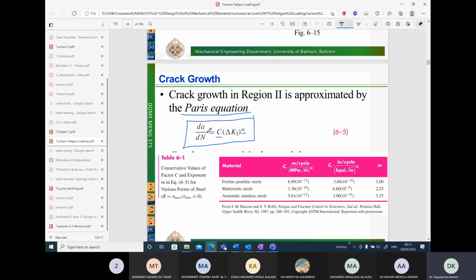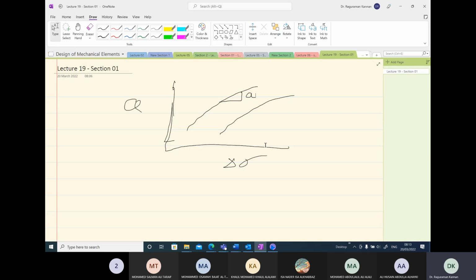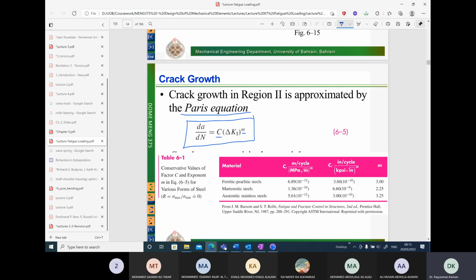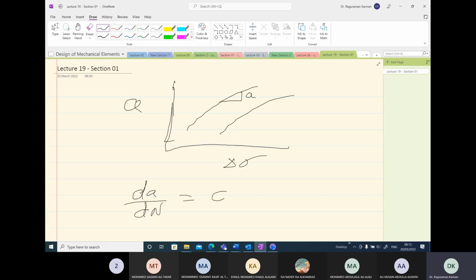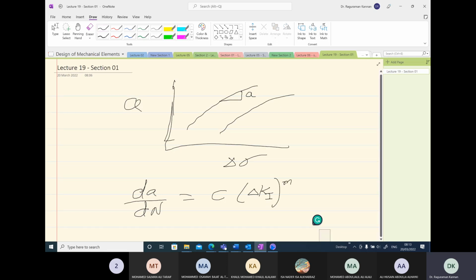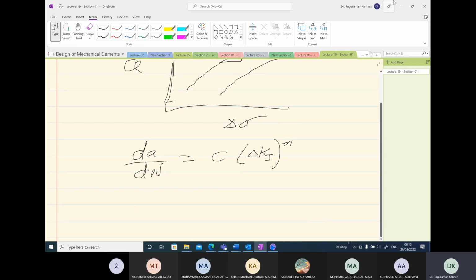So how do I find the number of cycles to failure, or the life of the specimen, from this equation? By rewriting this equation and then integrating it. So we can rewrite dA over dN as C times delta K to the power m. Take dN to one side and take all the other terms to the other side.